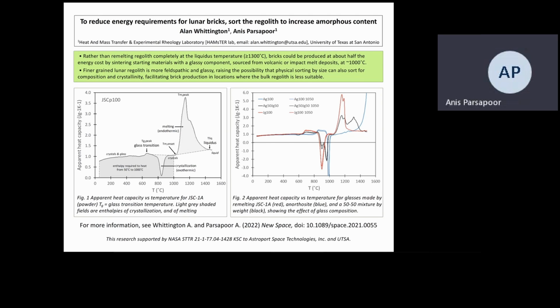The graph on the left side shows apparent heat capacity versus temperature for JSC-1 when measured as a powder. The heat capacity slowly increases until the glass transition at about 650 degrees. This is followed by an exothermic peak at 845 degrees and an enthalpy of crystallization of about minus 52 joules per gram. The melting peak begins at 1020 degrees and reaches a maximum at 1145 degrees centigrade.